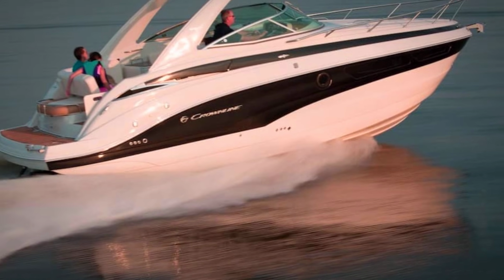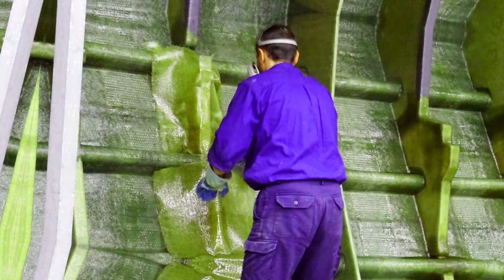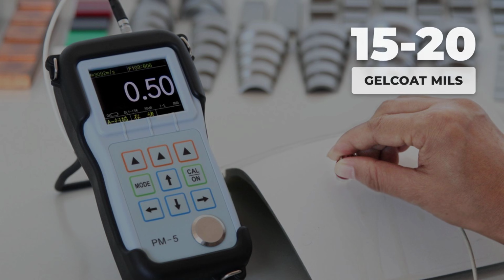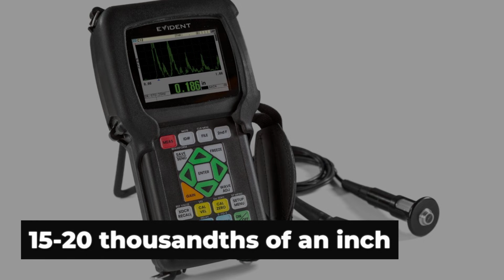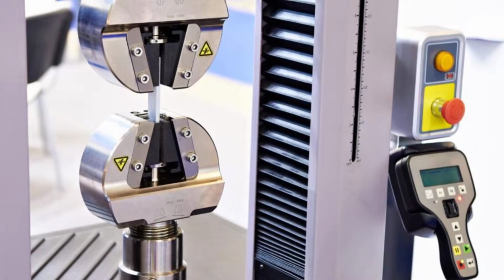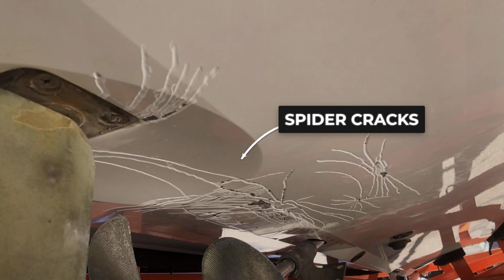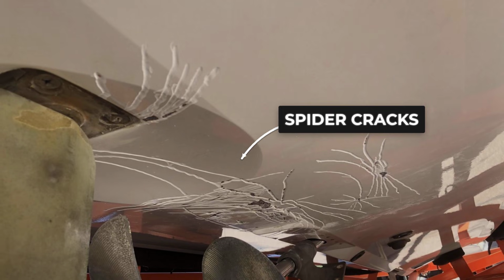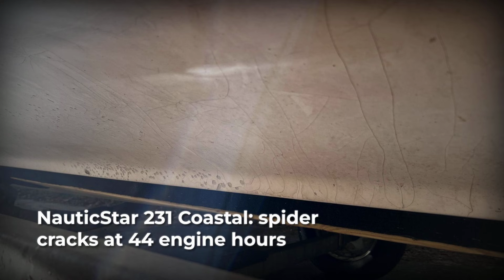But the transom is only part of the problem. Let's talk about what the hull itself is made of. Proper gel coat thickness is 15 to 20 mils. That's 15 to 20 thousandths of an inch. Gelcoat is brittle by nature. It shrinks 4 to 7% during cure and has less than 1% elongation. If the thickness varies, and on budget boats it always does, you get spider cracks. A Nautic Star 231 Coastal developed spider cracks at 44 engine hours, not 44,000 miles, 44 hours. Brand new Seaborne boats showed spider cracks sitting on the dealer lot.